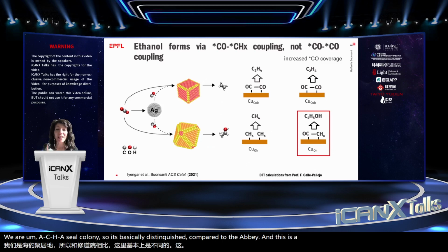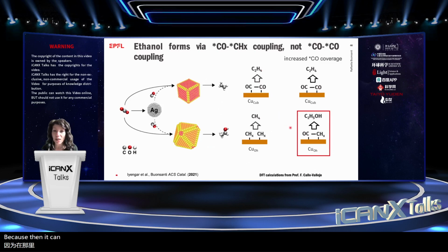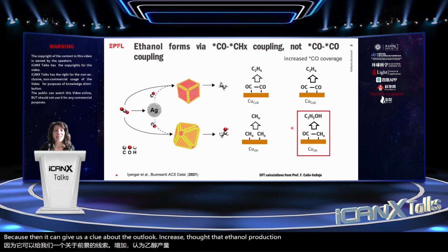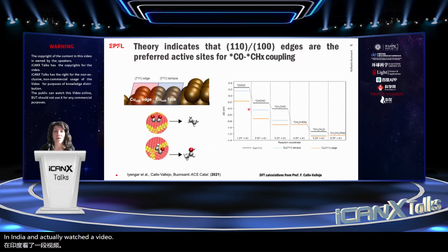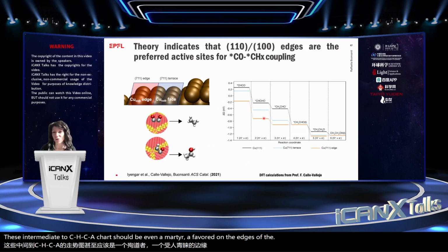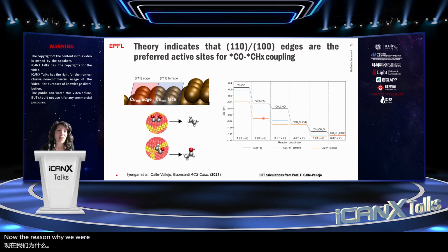And this is key information because then it can give us a clue about how to increase further ethanol production. And actually what Federico found is that this intermediate CH-CHO should be even more favored on the edges of the cubes. Now, the reason why we were actually not seeing more ethanol on the cubes was attributed to the fact that the ratio between the facets and the edges was too high.